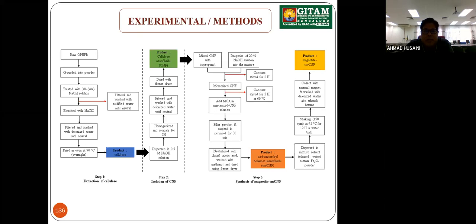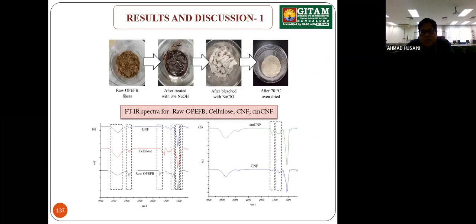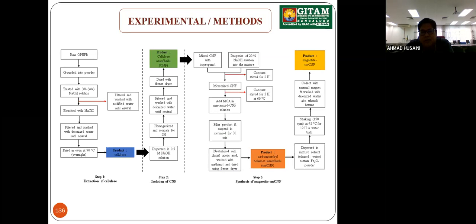Next, this is the experimental method, which I divided into three steps. Step one is the extraction of cellulose, where the raw OPEFB will undergo a pretreatment process and then produce cellulose. The product obtained is cellulose, which will then undergo isolation to produce cellulose nanofibril, done using the alkaline solution, sodium hydroxide, and at the same time we use a homogenizer and sonicator. Next, we move to the synthesis of magnetite carboxymethyl nanocellulose, where we use carboxymethylation followed by the solvothermal technique. Next.